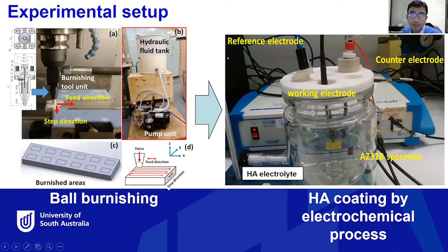And next we have done the hydroxyapatite coating. We have used a very standard 3 electrode potentiostat to deposit the HA coating on top of the burnished sample. This is the sample you can see here, and we have the hydroxyapatite electrolyte in the beaker here. So this is a very standard process we have considered.